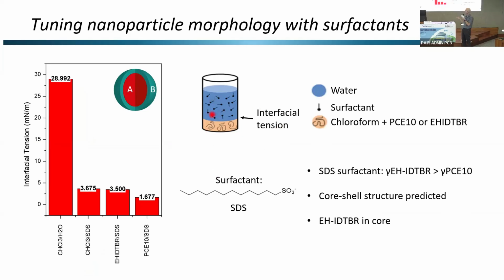So we create this emulsion with surfactant. Usually we have water as a dispersion, and we dissolve our two components in chloroform. And we use a typical surfactant here. This is SDS. You've got your long fatty tail and your ionic head. And so when we look at the interfacial tension, of course, this is chloroform and water. It's a very high interfacial tension. And when you add your surfactant, of course, the interfacial tension drops. That's what you would expect from a surfactant.